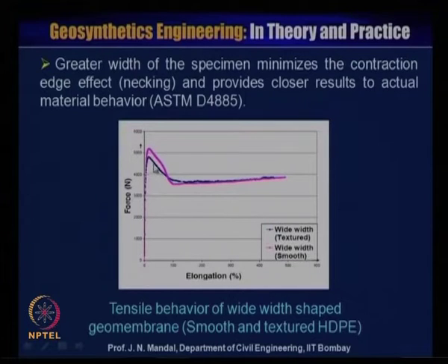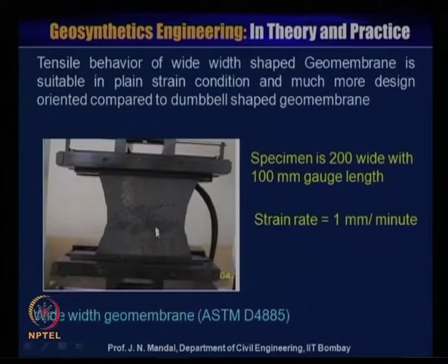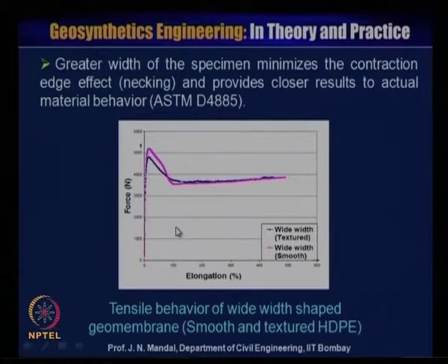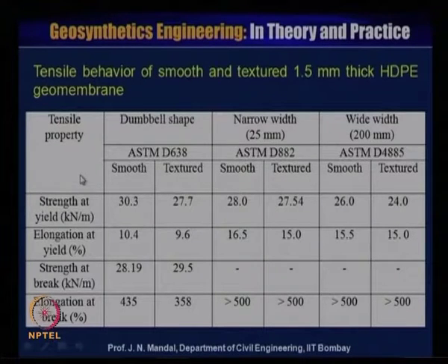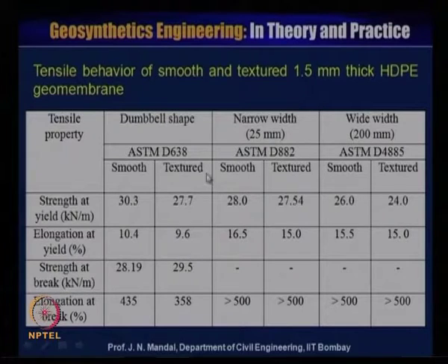So, the greater width of the specimen minimizes the contraction edge effect, that means necking, what you can see here, and provides a result closer to the actual material behavior. This is as per ASTM D4885. So, you can see some of the results of the smooth and textured behavior, for which the thickness of the HDPE is 1.5 millimeter.